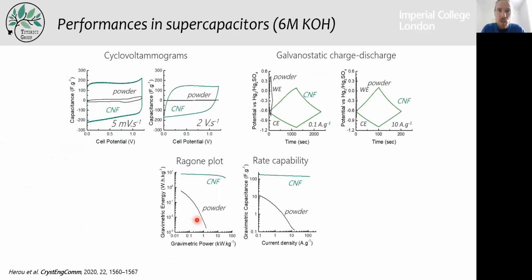So then we tested this in supercapacitors, and we can see the cyclic voltammograms. They are fairly rectangular, as I explained in the second slide. The powder shows much lower capacitance compared to the carbon nanofibers. Here you can see a slight hump on the CV that is mostly due to oxygen surface groups. At a higher scan rate of 2 volts per second, we maintain this rectangular voltammogram fairly well. That is the galvanostatic charge-discharge, where we observe a fairly triangular profile, and compared to the powder, the discharge time is much higher.